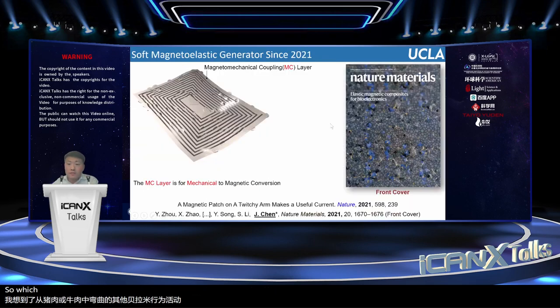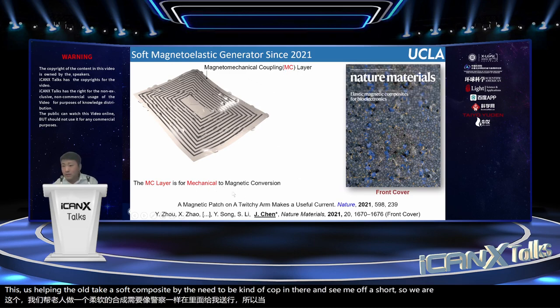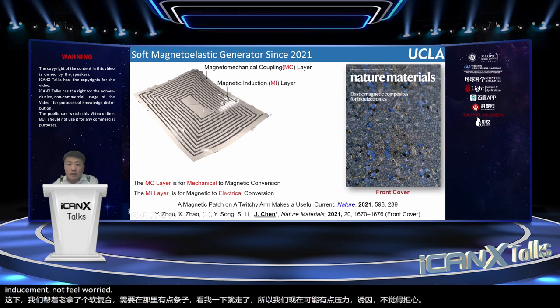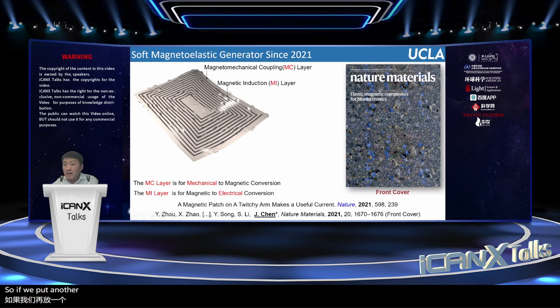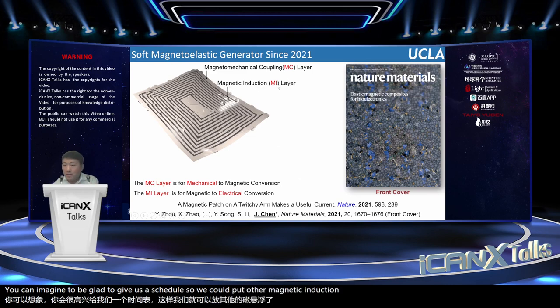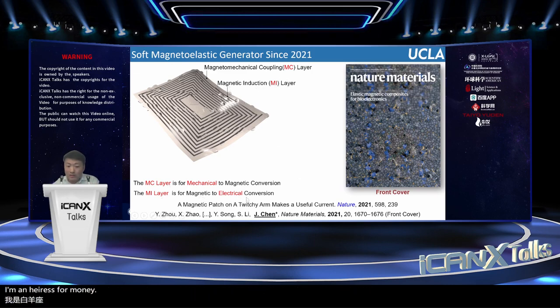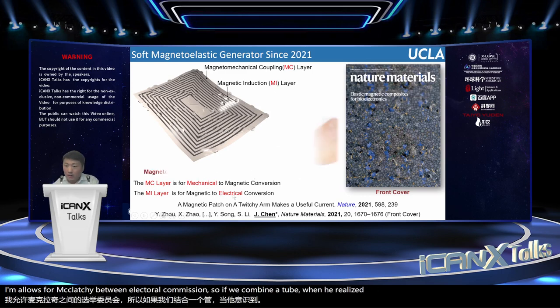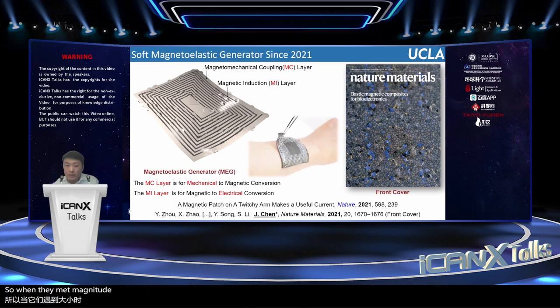So we took a further step to develop a magnetoelastic generator. We take this magnetoelastic coupling, a soft composite magneto-mechanical coupling layer, MC layer for short. When you apply mechanical pressure, that will induce magnetic field variation. If we pattern another layer, for example a metal coil, we can use liquid metal to make the device stretchable. We call it the magnetic induction layer, MI layer, which is for magnetic to electrical conversion. If we combine the two, we can realize mechanical to electrical conversion. So we name it the magnetoelastic generator, MEG for short.